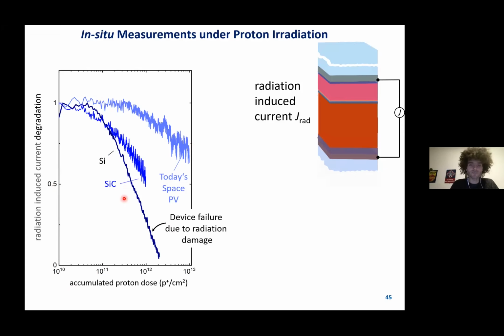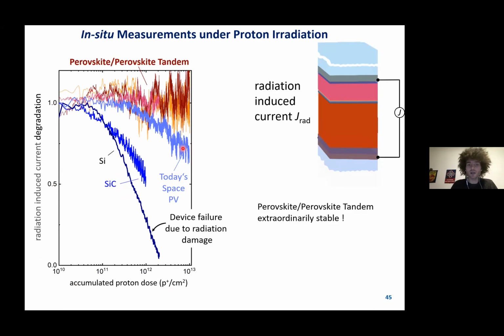And in all of them, I see the accumulation of defects leading to a degradation. However, when we look at the perovskite-perovskite tandem, it's extraordinarily stable. Most importantly, here, I'm now going up to a proton dose of 10^13. And before, I've been looking at devices after around 2 times 10^12 protons. So I'm a factor of 5 more damaging now.